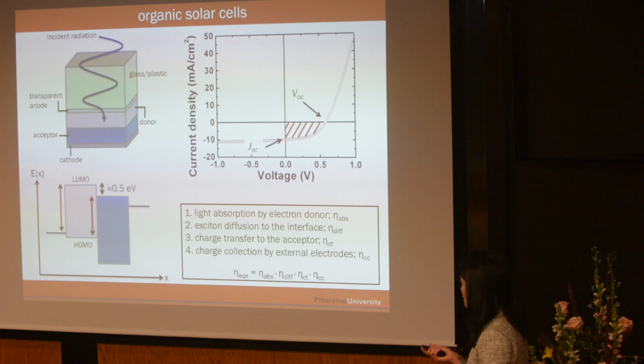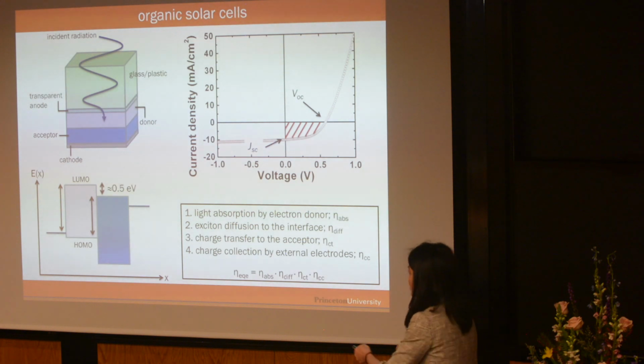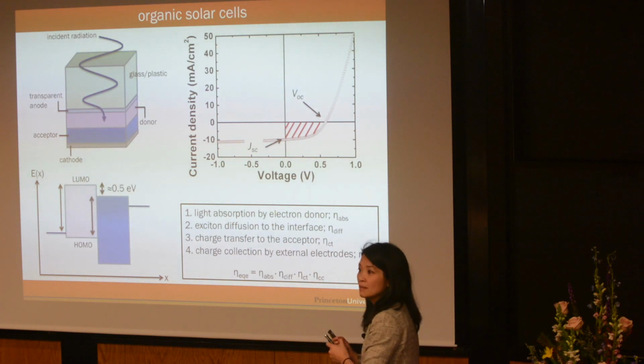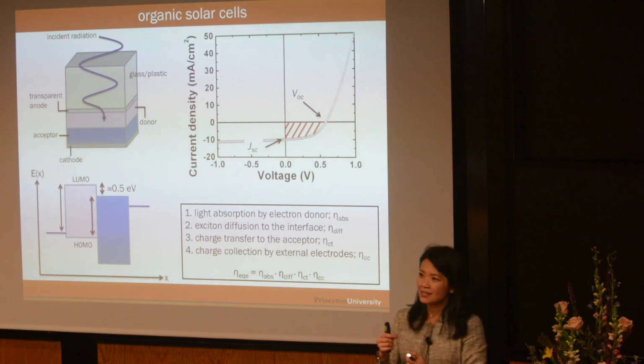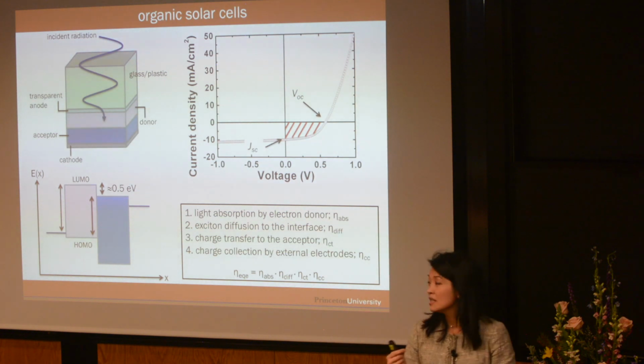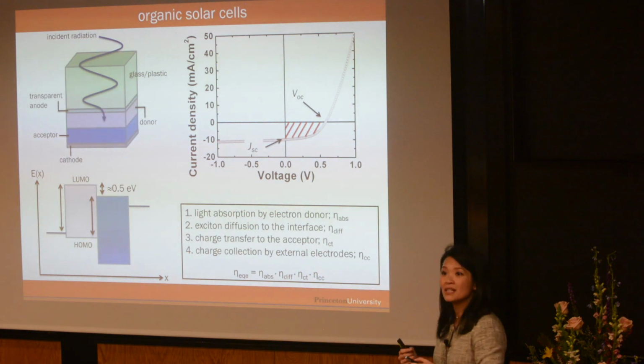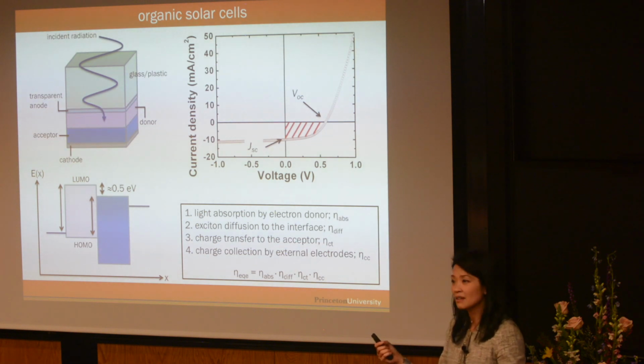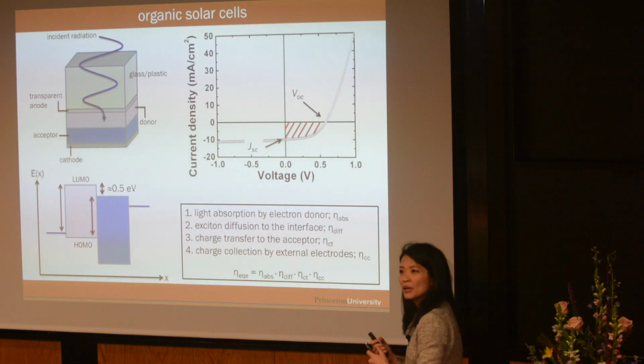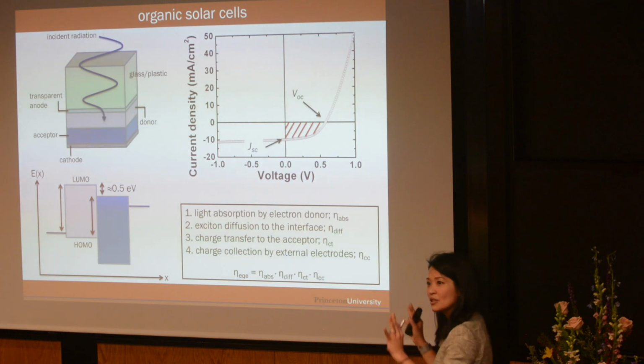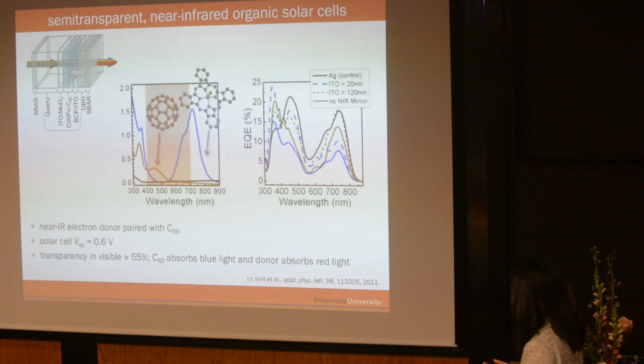The other important thing to remember is for these organic solar cells, this LUMO-LUMO energy offset is important. I mentioned that you have an exciton and you need to split this exciton. So this LUMO-LUMO energy offset is what drives the splitting of the exciton. And that typically needs to be at about 0.5 eV, okay? So those are the constraints of making solar cells.